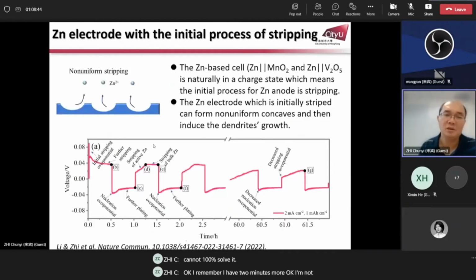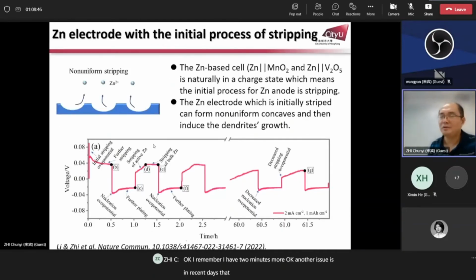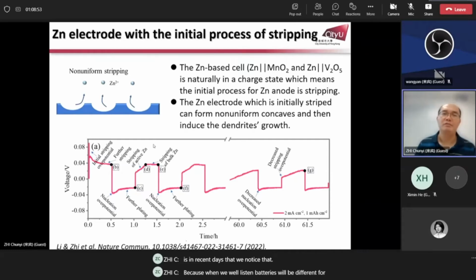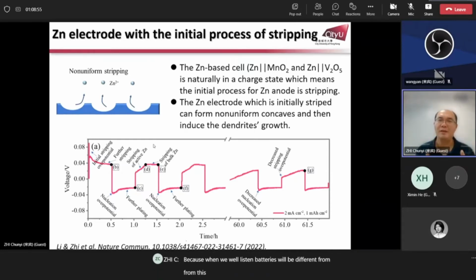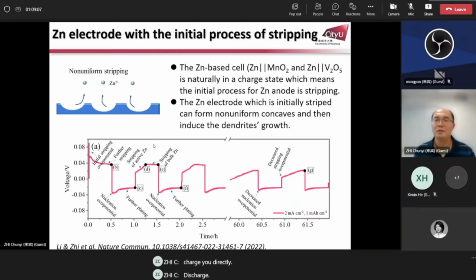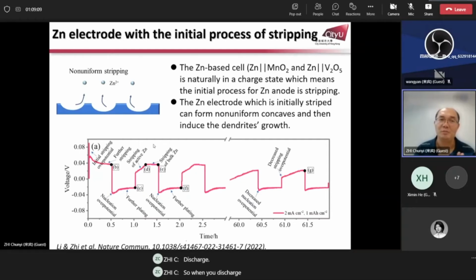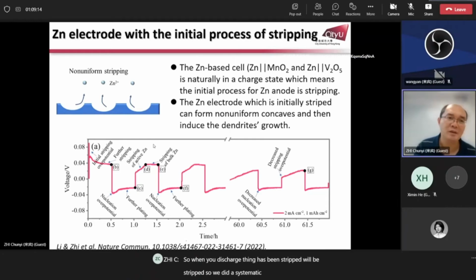Okay, another issue that we noted in recent days is that lithium batteries are different from zinc batteries. When you fabricate zinc manganese oxide or zinc vanadium oxide batteries, you do not need to charge, you directly discharge. So when you discharge, zinc is being stripped. So we did a systematic, detailed study on the stripping process of zinc.